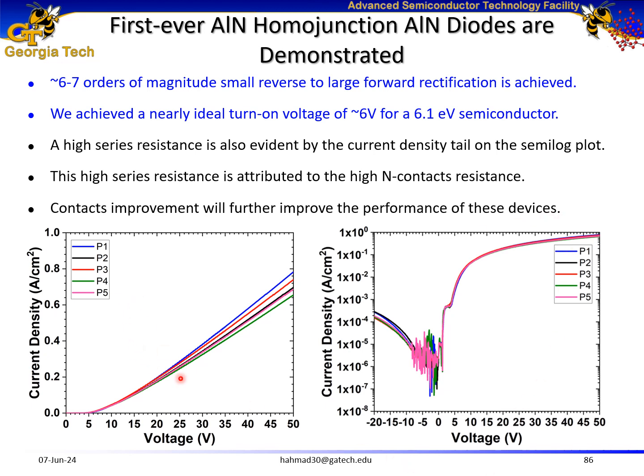In this slide, I've shown the JV characteristics, both forward and reverse bias, for these homojunction aluminum nitride diodes. I achieved approximately 7 orders of magnitude rectification for these diodes, and we achieved a nearly ideal turn-on voltage of approximately 6 volts for a 6.1 electron volts semiconductor. However, we see a high series resistance evident from the long tail of the semilog plot, which is attributed to the high N-type contact resistance, and with improvement in the contacts, we can achieve even higher performance for these devices.